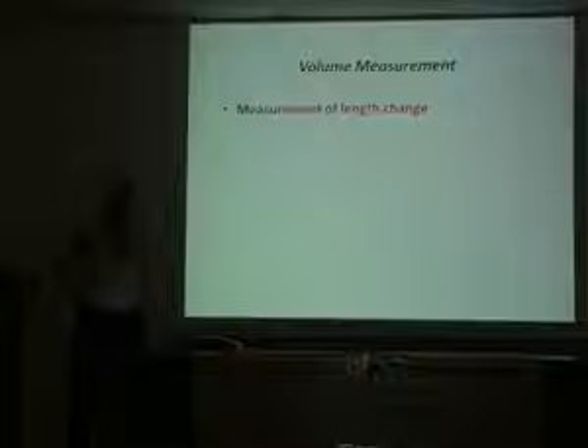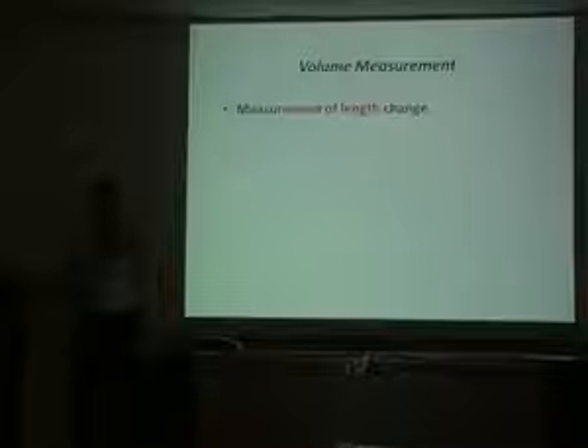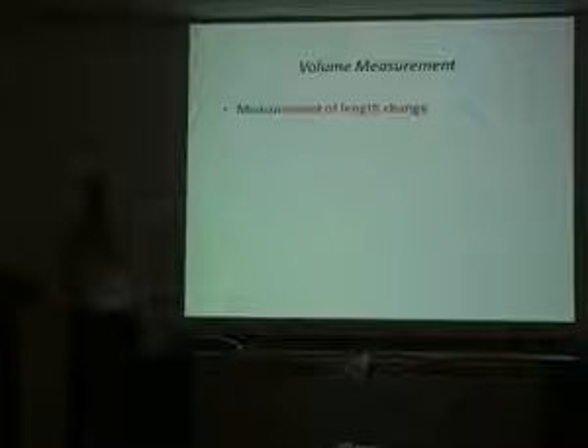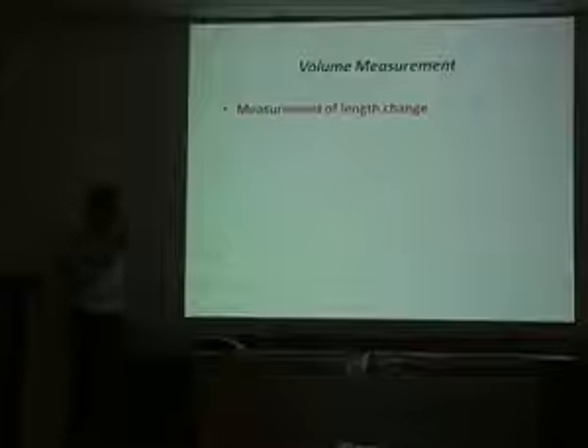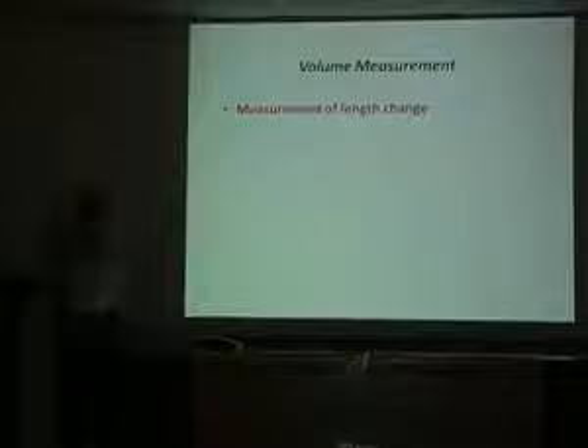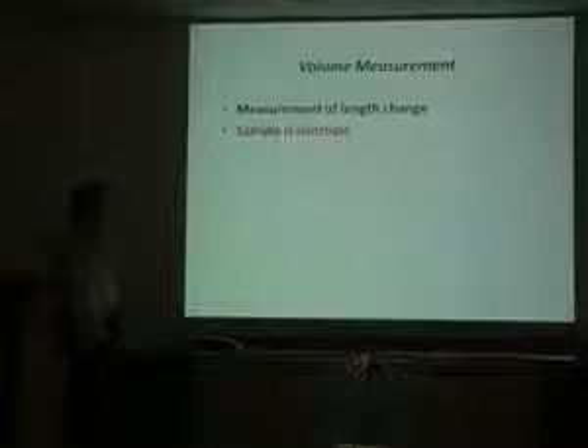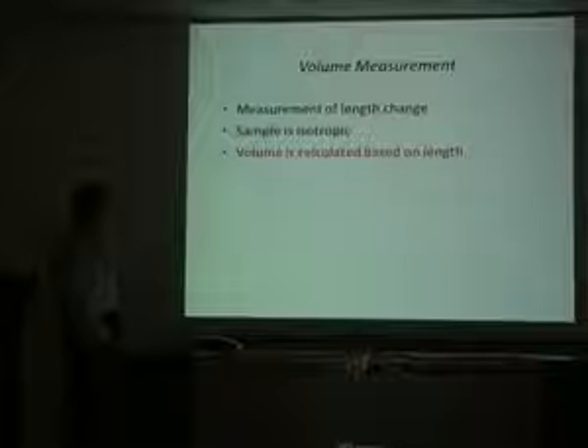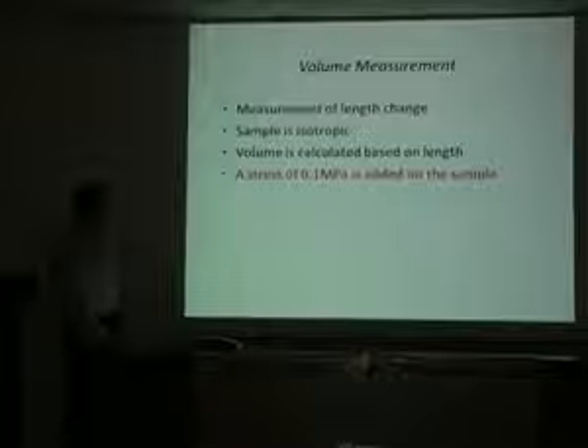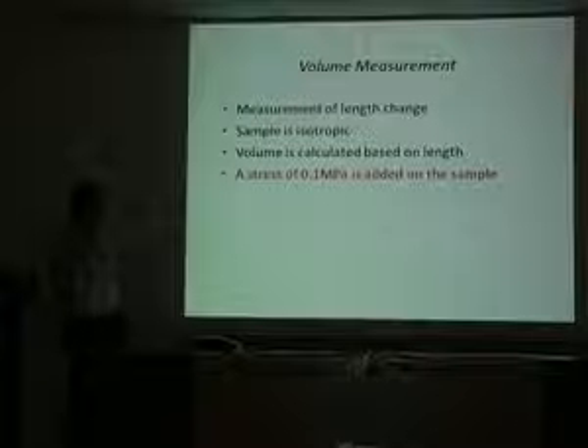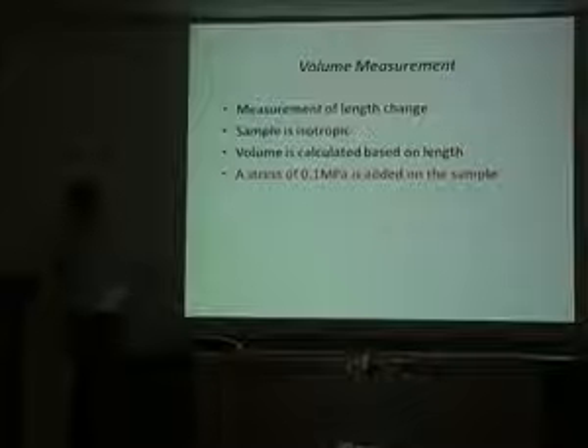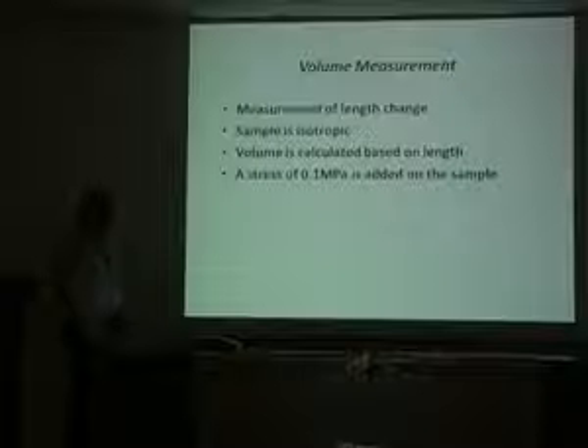So for the volume measurements, it turns out these are thin films, I can't put them in a dilatometer, so I'm going to measure length change. But we chose our polymer so it had a solid structure because it's cross-linked. It's isotropic. The volume changes based on length. And because of the way we do it, we have to straighten the film. There's a very small stress on the sample as we do it.